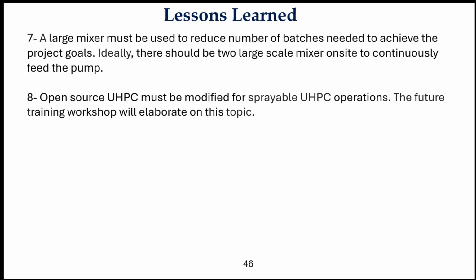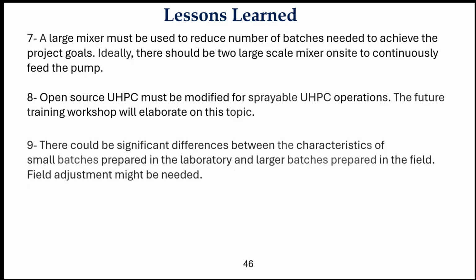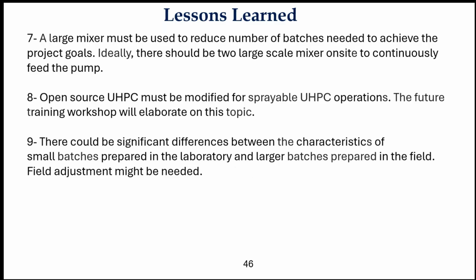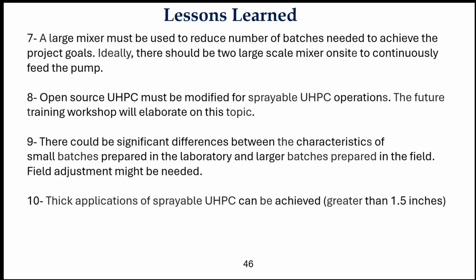Now, the open source UHPC is available, but the sprayable UHPC is not. Open source UHPC needs to be modified in order to use it for spray applications. Another thing you need to notice, there could be a significant difference between what you do in the lab with a small mix and the large batch. You can get completely different timing for the time needed for mixing and so on. You can apply large thickness, I would say probably an inch and a half. Probably you can do more than that.